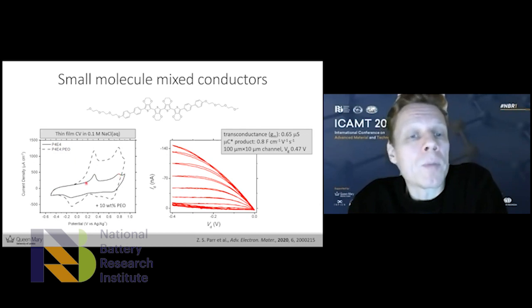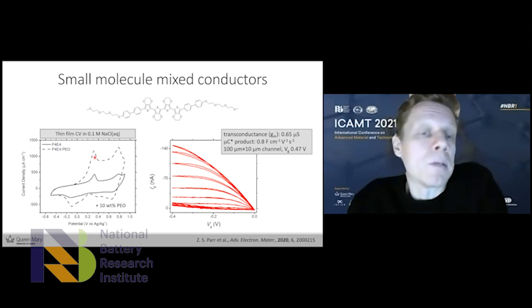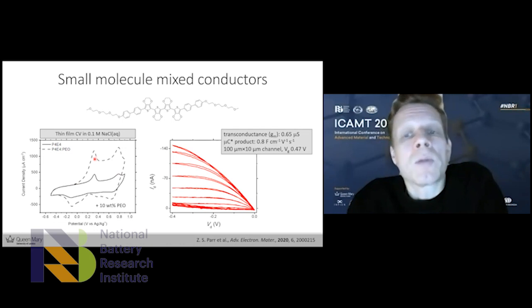Another thing we observed was that when we blend in a PEO, a passive polymer matrix, we see much higher current responses, we see better film formation properties. So that turned out to be a key in getting good OECT devices for this material. So we blend in 10 weight% high molecular weight polyethylene oxide, and then we get good working OECT devices.